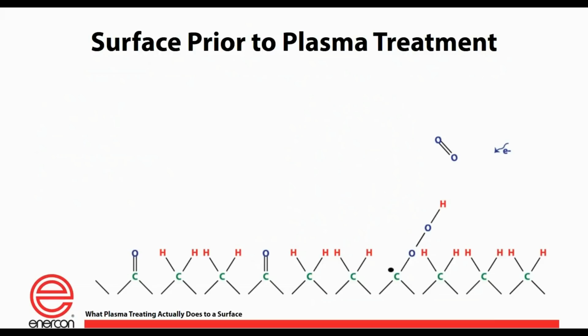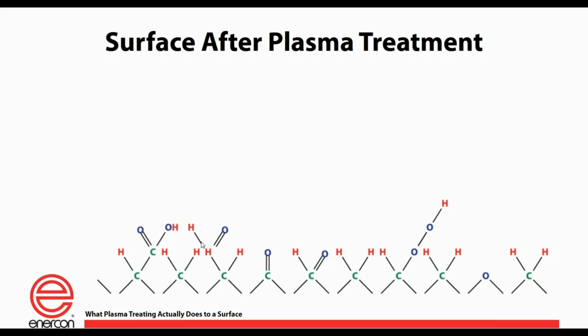Now, this is a molecular chain, the outermost molecular chain of a hydrocarbon in this case. And we're seeing what happens when you start to treat it with plasma. This is prior to plasma treatment. You see that there's one functional group, one OH group over there on the surface, but most of the other are nonpolar groups on that surface, and you're not going to have a very good bond to that. But after treatment, with the next slide, you'll see that you're starting to add more OH groups, O2 groups, and these are the polar groups that you're adding, again, on the molecular level to the outermost one or two molecular chains in that material, and you are going to increase the surface energy of this part.